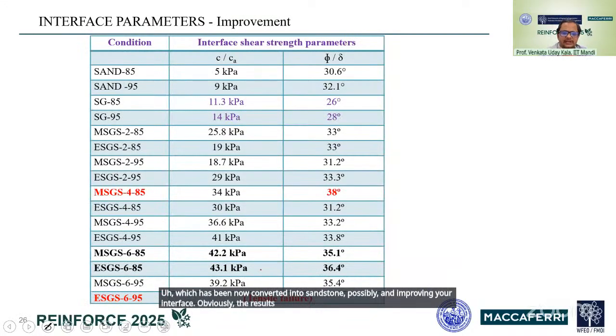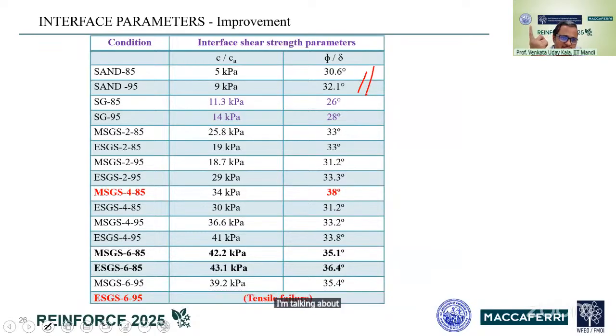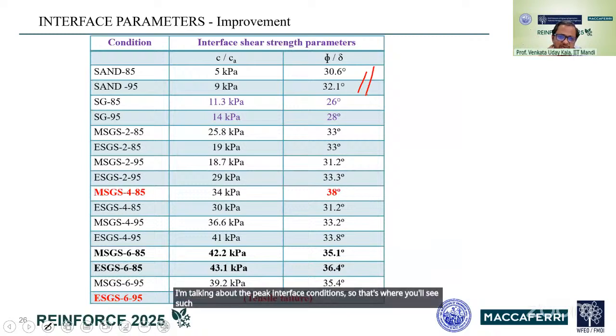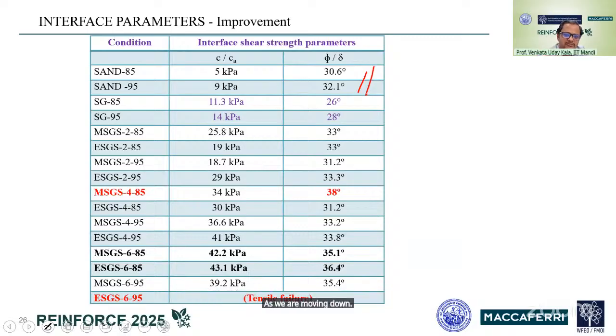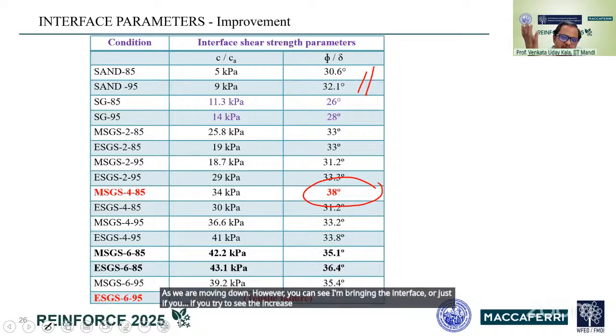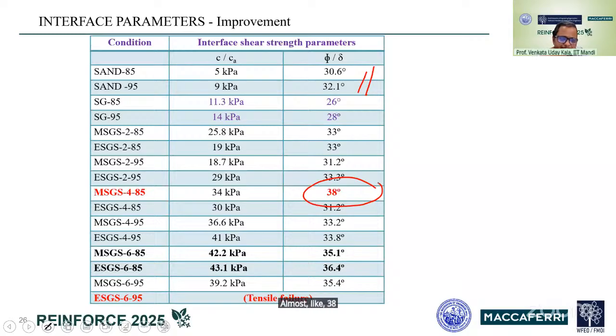Obviously, the results will be interesting to see that the interface which was only developed between the sand and the interface was roughly around 30 degrees. Don't mind, I'm talking about the peak interface conditions. So that's why you'll see such high values, while the values can be comparatively low as we are moving down. However, you can see the increase which is happening from the 30 degrees interface to almost 38 degrees. 38 degrees, the interface is getting generated when we are talking about biocementation, which is improving the condition.